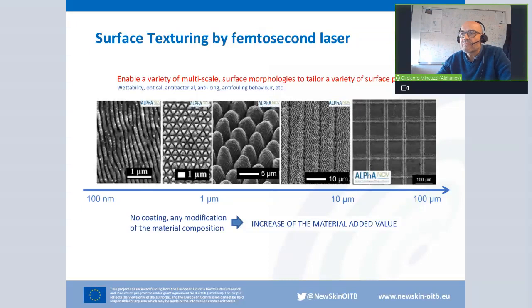I would say that ultra short pulse lasers, and femtosecond lasers in particular, are one of the key technologies to generate a wide variety of surface structures at the nanometric and micrometric scale. Here you see, from left to right, some of the structures that we can generate on the surface. From nanometric structures on the left, 1 dimension, 2 dimension, to micrometric structures with the so-called DLIP that can generate these spikes that you can see here in the middle. We are able to generate hierarchical structures, so structures at different scales from micrometric to nanometric, and we can also manage another technology that produces structures in the range of 100 microns.